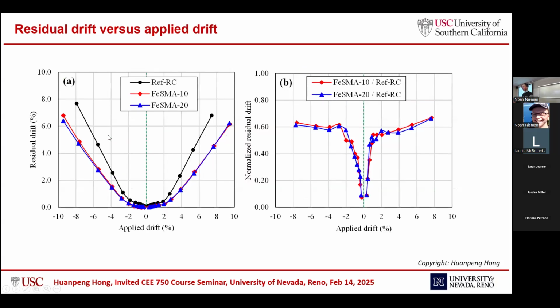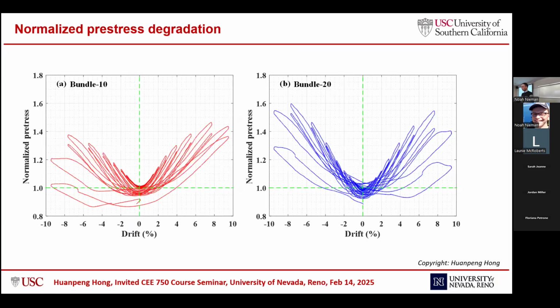So here we extracted the residual drift versus the applied drift. For example, at around 8% applied drift, the residual drift of the reference RC is maybe around 7%. But for the two proposed columns, they are around maybe 4.5%. It's only around 60% of the conventional design. So this means the proposed column is definitely feasible and improves the seismic resistance of the column.